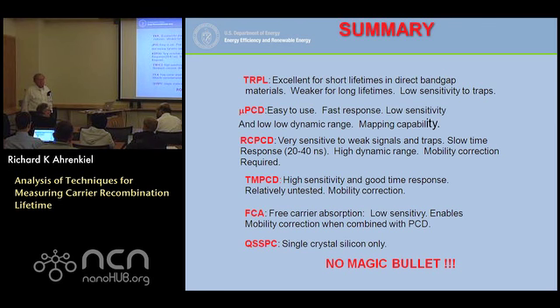Have you noticed, obviously you've measured lots of different samples using lots of different techniques, and you mentioned that there's such a thing as too low injection and too high injection. Have you noticed a rule of thumb for where that window is on either side of the measured carrier density? What I would do ordinarily, usually I have some kind of variable attenuator and just start looking at the pulse, going as low as possible, thinking the lowest injection that I can measure is probably more indicative of the quality of the sample and the real low impurity content. But then crank up the intensity gradually and look at how things change.